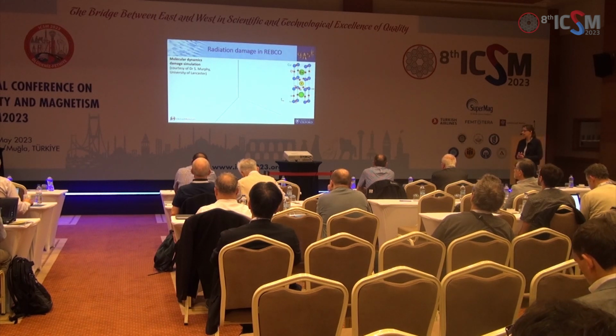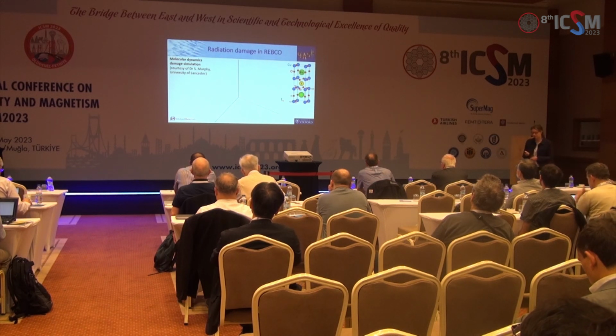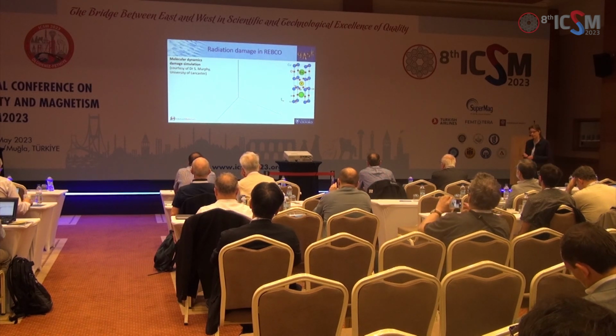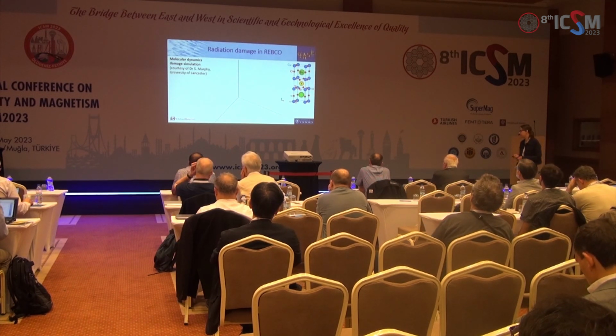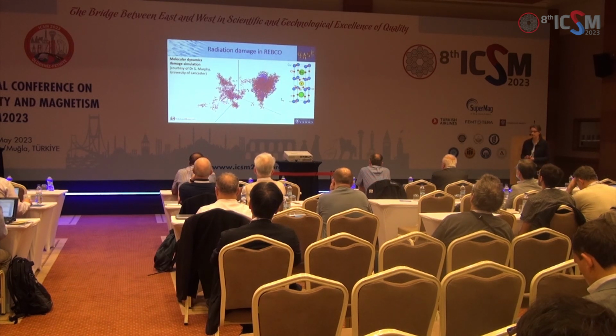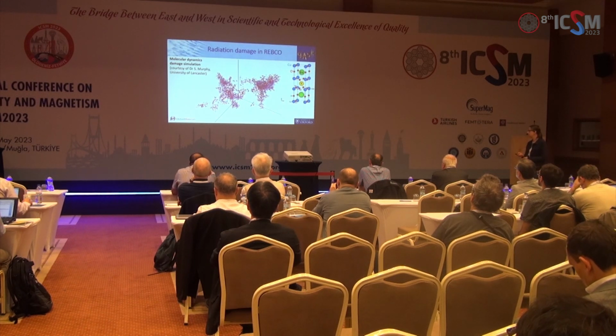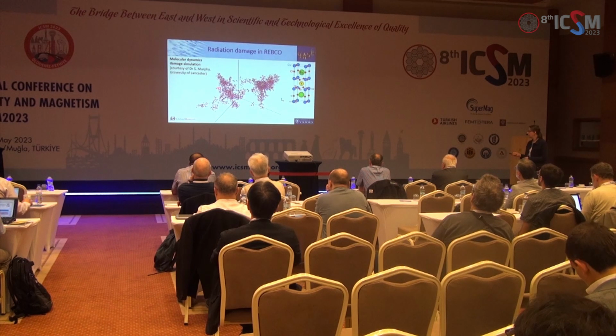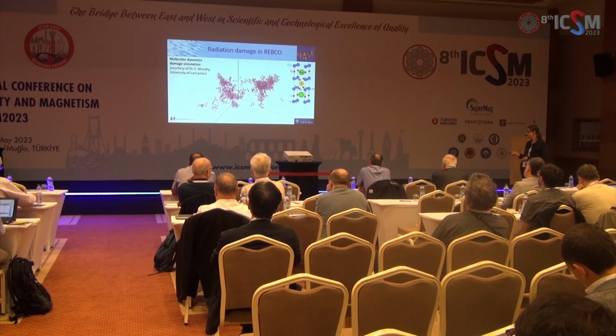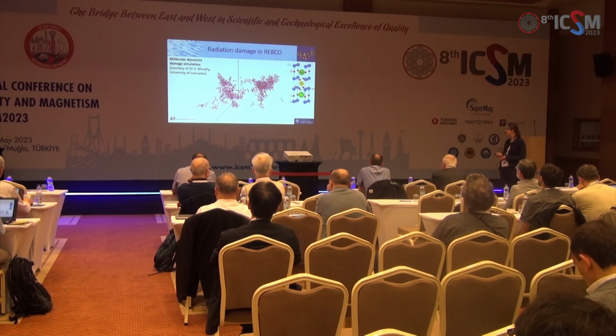If we look at a molecular dynamics simulation done by Sam Murphy in Lancaster, you'll see what happens when a projectile hits something like REBCO. So what you'll see is one projectile coming in, knocking one atom in the structure, and then every coloured dot you see will be an atom that's been pushed out of place. So you get something like this happening. This is this damage cascade I was talking about, where each of these dots is something that's in a position where it didn't start and isn't on a lattice site anymore. So you end up with these regions like this, which are these cores of the damage cascades.